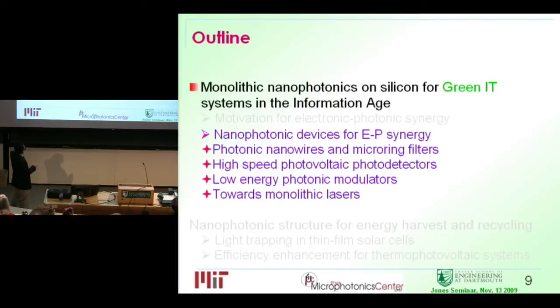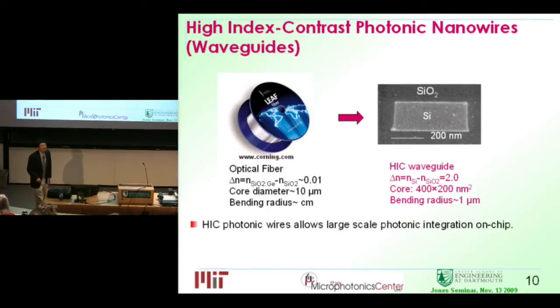Okay, we'll go through some of the really important photonic devices here. We'll start with talking about wires. Just like electronics, you have copper wires. Photonics also have a wire, but it's guided by the index difference through total internal reflection. Basically you have a core material with an index higher than the cladding, and when the incident angle is larger than the critical angle for total internal reflection, then you get waveguiding in this wire. But the problem with the optical fiber is that this index contrast is very small.